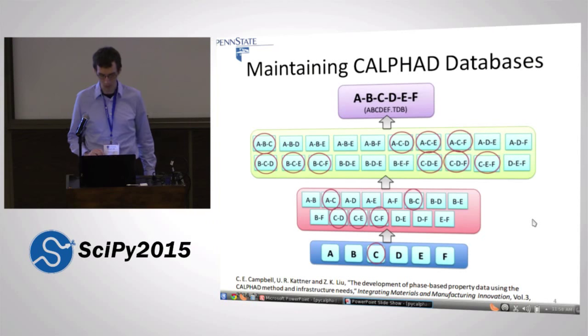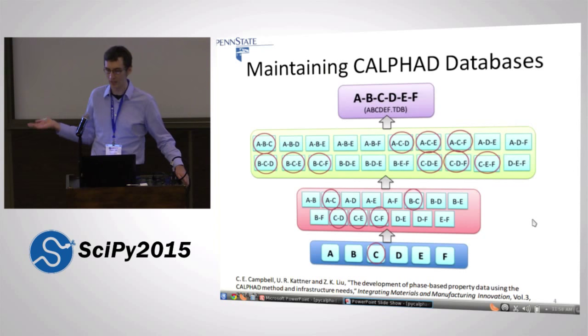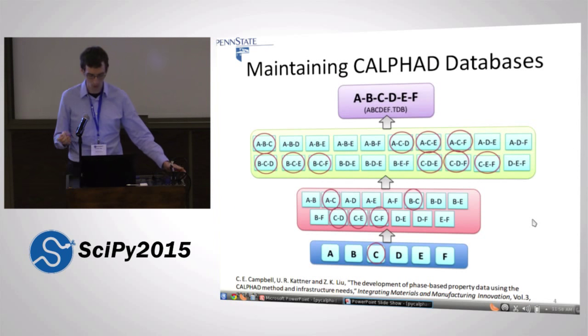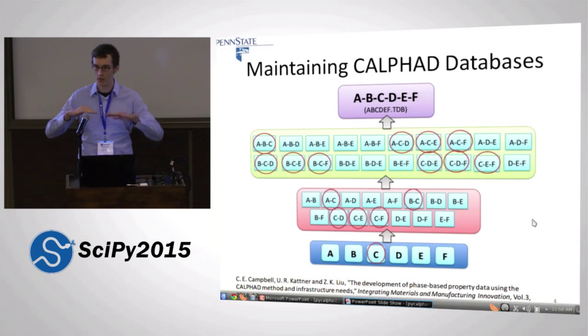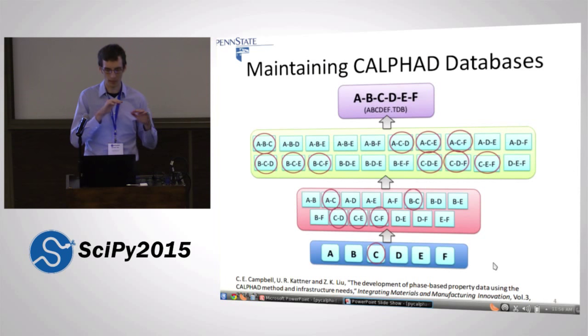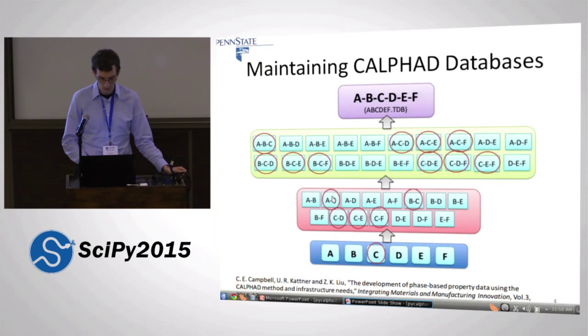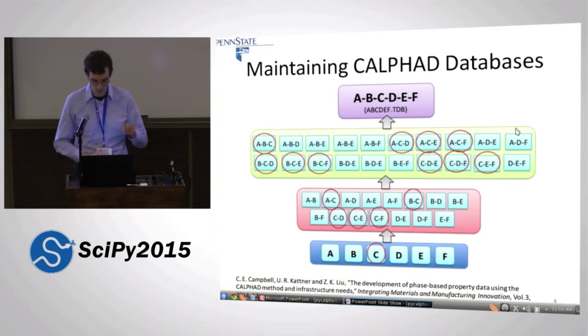There's also a practical reason why we care about reproducibility in the CALPHAD community: the problem of maintaining CALPHAD databases. Here I'm depicting a hypothetical six-component system, ABCDEF — you could imagine elements like nickel, iron, cobalt, chromium, and so on. CALPHAD databases are built starting from the pure elements, then we fit the binary system, adding parameters for binary interactions, and then ternaries. Thankfully, nature cut us a break — we don't have to go to higher order; linear combinations of the ternaries basically covers metallurgy.